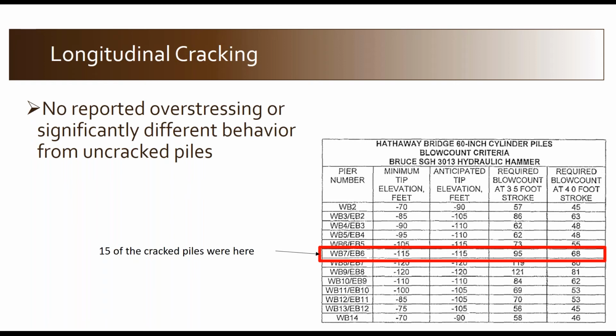It turned out they were at the upper end of the ranges of length and blow counts for the driving criteria, but they were not the extreme. They weren't the longest. They weren't the ones we hit the hardest necessarily. It was interesting to note that about three quarters of them were clustered at one pile cap near the center of the bridge, or two pile caps for the two separate bridge structures, but at essentially the same location on the two adjacent bridges.